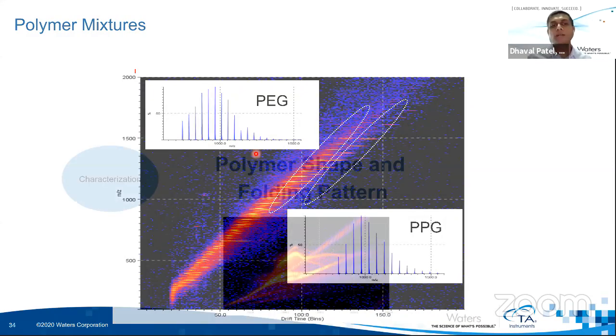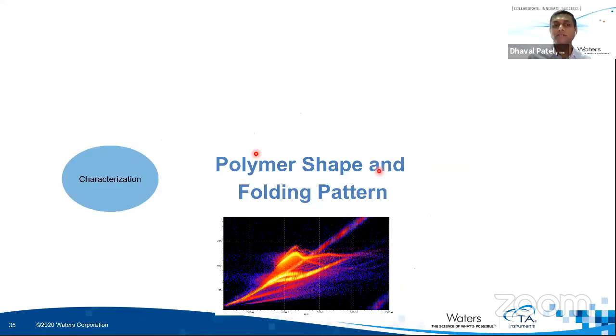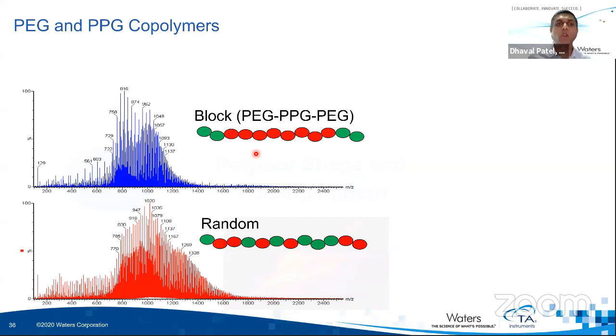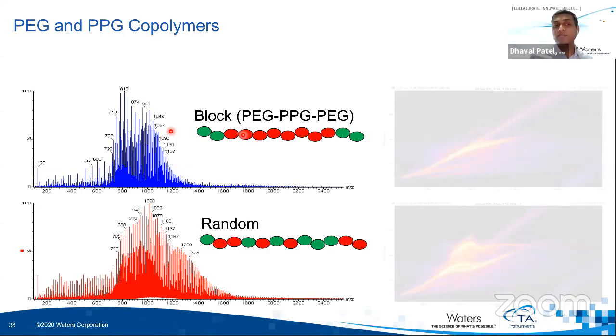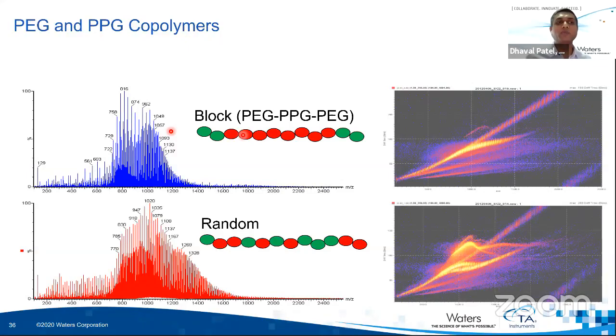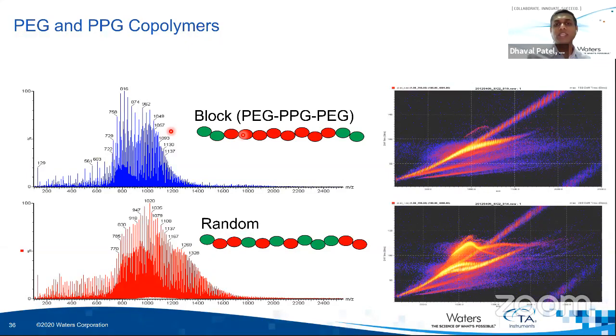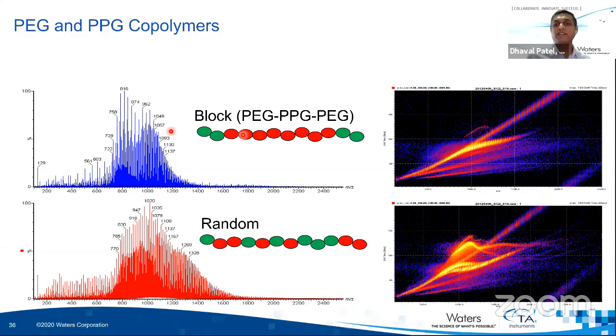How about polymer shape and folding pattern? We can also characterize this by using mass spectrometry with ion mobility. To give you an example, a block copolymer and a random copolymer, okay? Again, if you have a mixture of these two in a blend, it's very difficult to analyze whether it's a block copolymer or random copolymer. But when we look at this data by doing the ion mobility mass spec analysis, we can see that they give you a different pattern, okay?